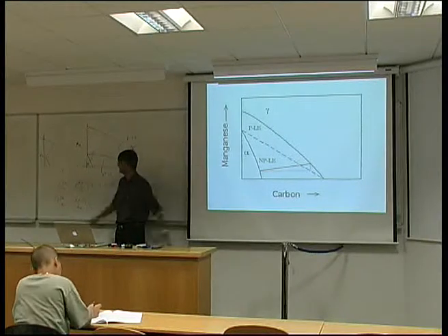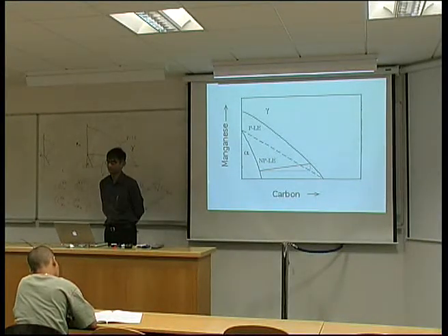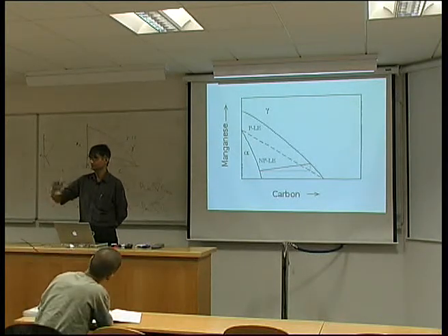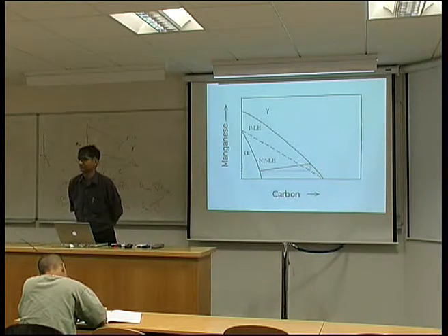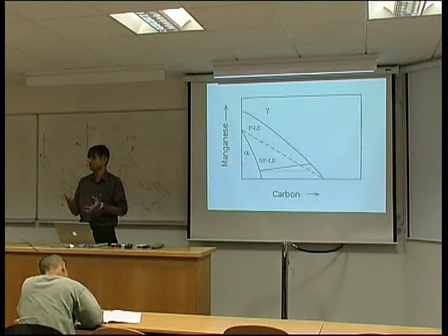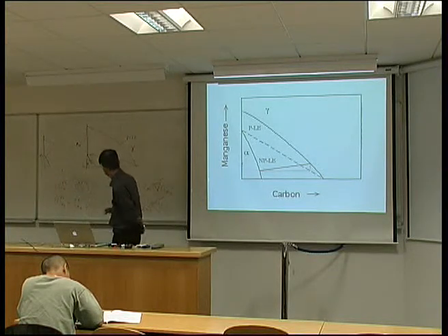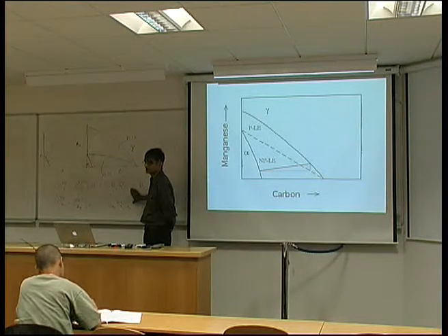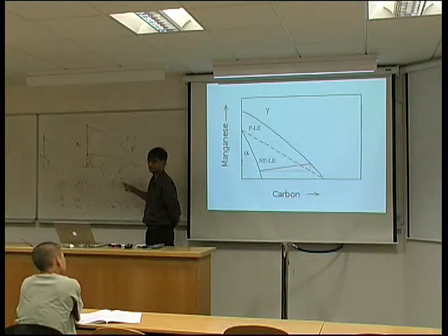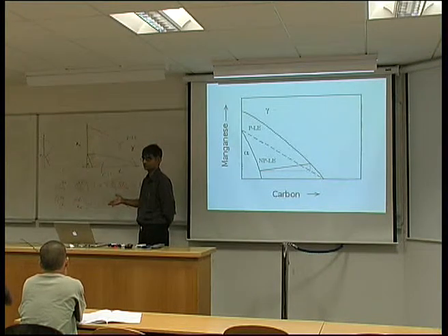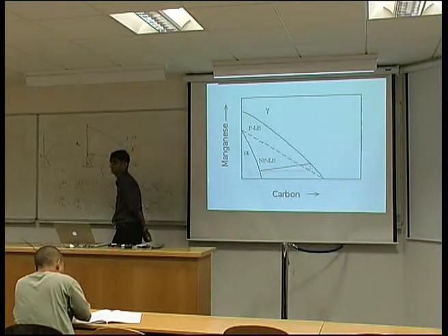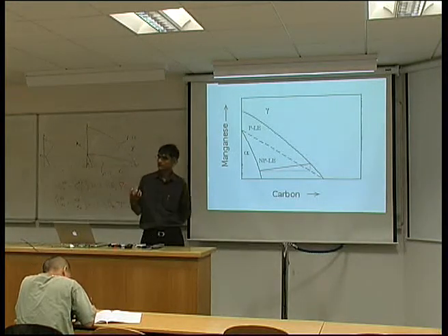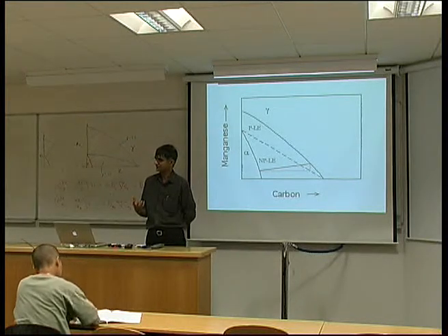Here, the same diagram that we did. If you try to do the other way, it simply doesn't make physical sense. So the system naturally chooses a manner which satisfies these two equations simultaneously, maintains mass balance. You know, you can't have both the austenite and ferrite being greater in manganese than the average composition. So that I think, you know, it appears difficult, but it's not really difficult when you think about it.